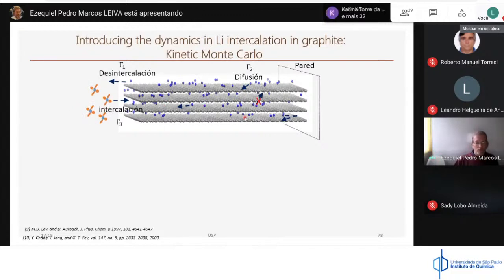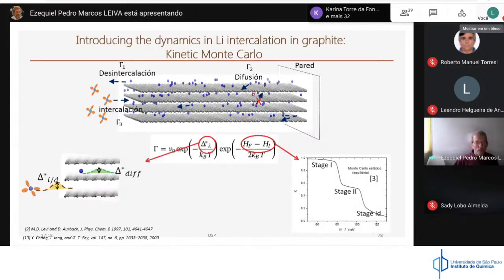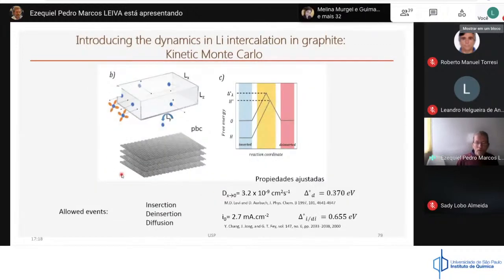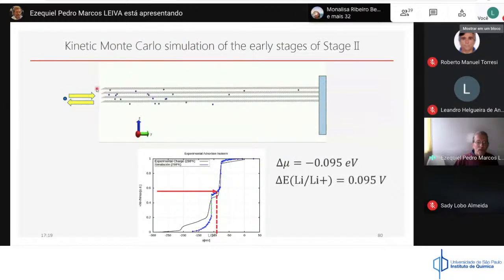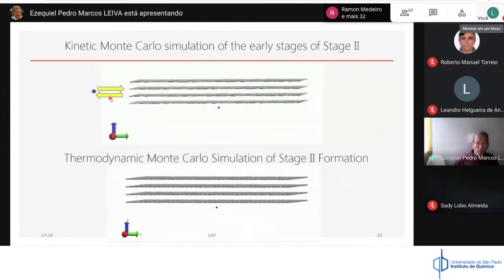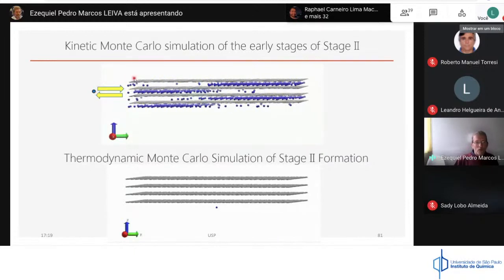And you have, of course, diffusion of the ions. So in realistic systems, in a kinetic system, you have to consider the migration, the diffusion of ions inside the layer, and the ion exchange at the interface. You can now write a number of rate equations, consider the energy, the activation free energy from this, and you have to set up mainly two barriers. One barrier for the diffusion of ions inside the material, another barrier for the exchange of ions on the surface. So with this model, you can go on, and you can see here how you are inserting ions from the left. Ions are not coming from everywhere like in ordinary Monte Carlo, but you are putting in the real physics. So we're putting the ion exchange on this side. And this is, again, a simulation where you let time advance, and here would be the filling of one half of the layer.